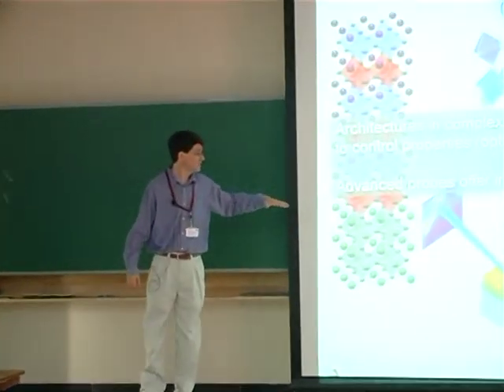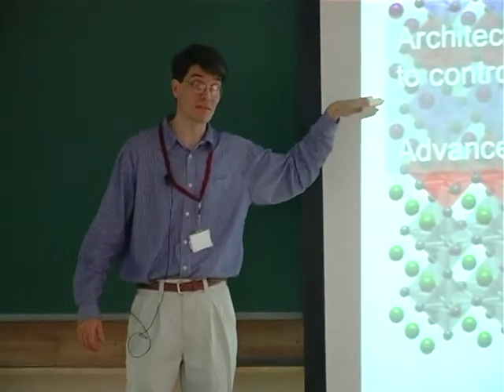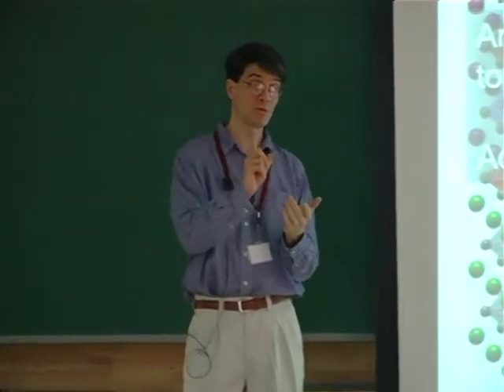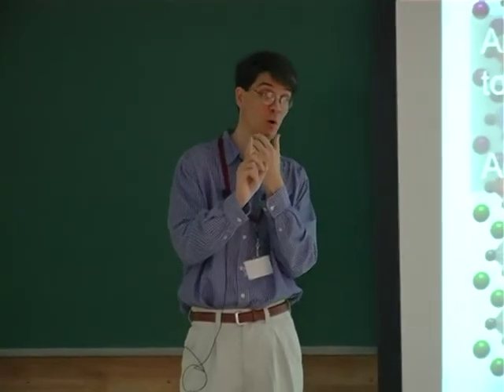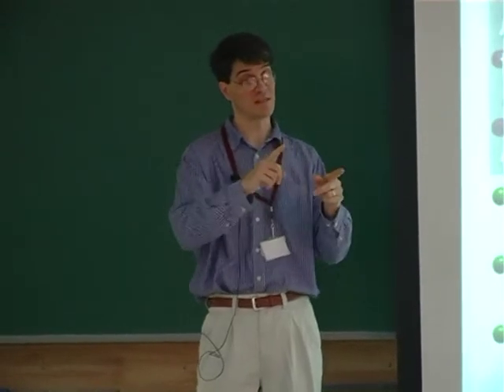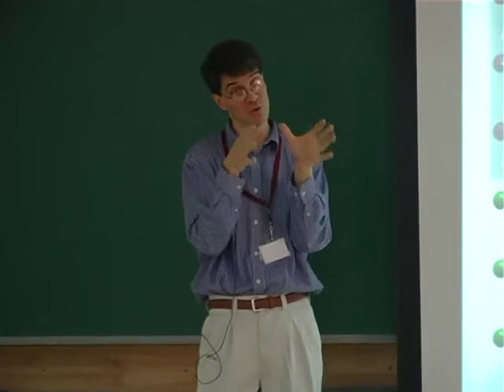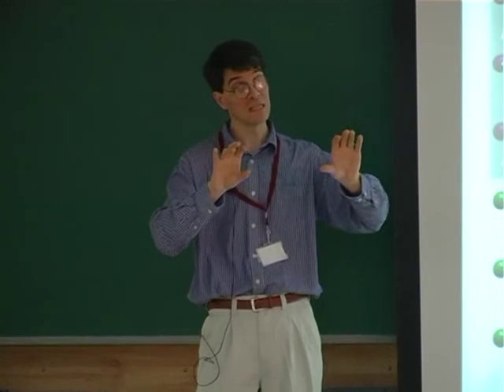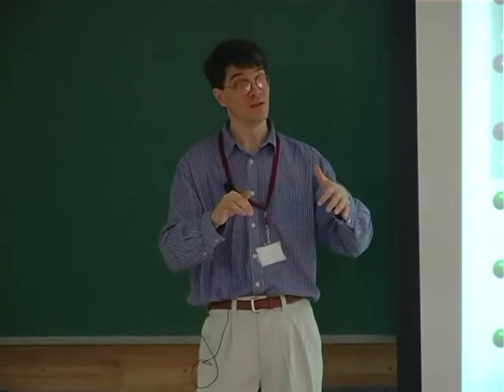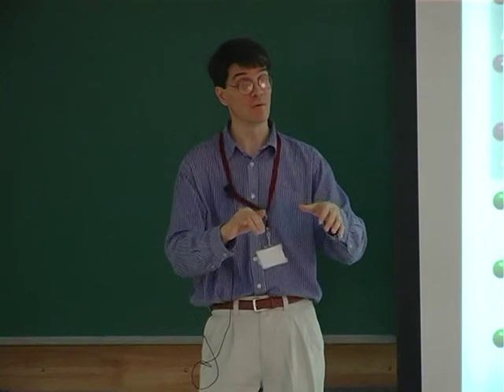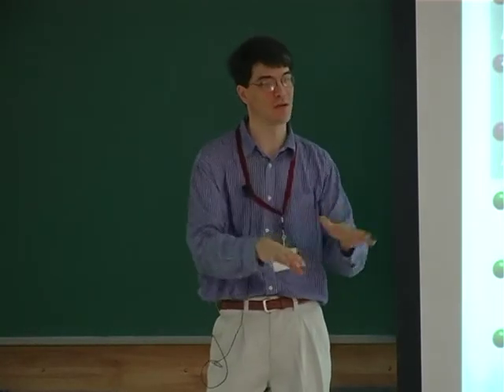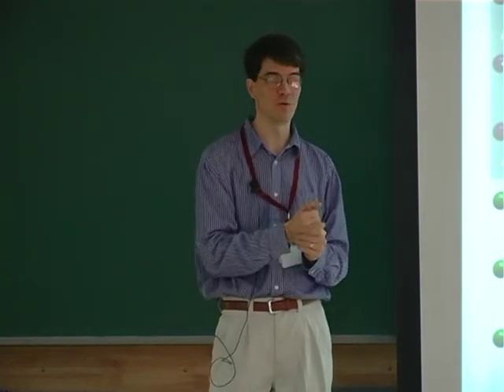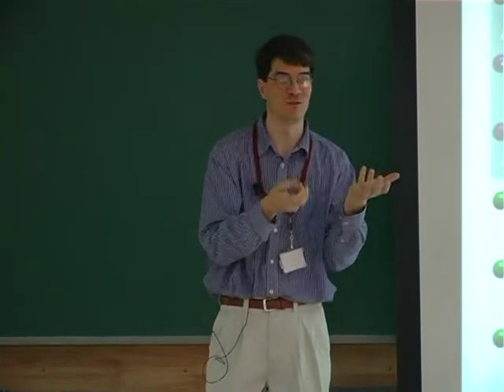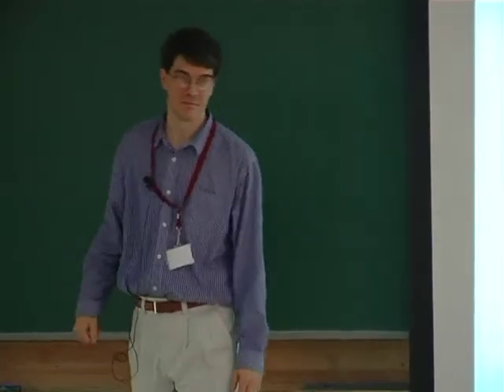I have no direct experimental proof, but my belief is that the interfacial layer also has magnetism because it becomes coupled to the ferromagnet below. The ferromagnet causes a canting of spins, so I believe you really have something more like an antiferromagnet that gets coupled to this ferromagnet below, for which we have evidence. So I don't think there's any superconductivity in that layer. But unfortunately, we don't have any direct proof to show that's the case.